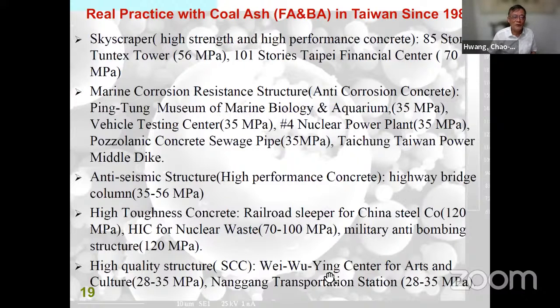And I also designed a high integrity container for nuclear waste, from 70 to 100 MPa. And also designed a military anti-bombing structure at 120 MPa. And then some high quality structures, I use fly ash and bottom ash as self-compacting concrete. Wei-Wu-Ying Center for Arts and Culture in Kaohsiung and the Nanggang Transportation Station. So that is a major project. But some other projects I also did for the construction site. Okay, next please.